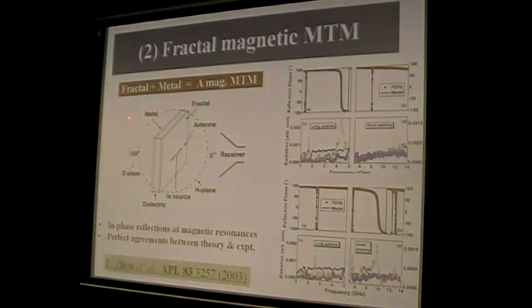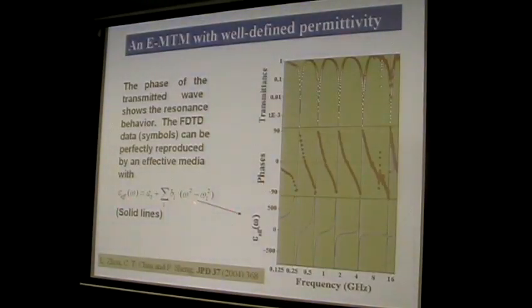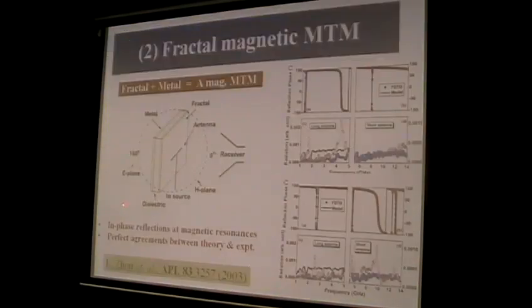Now I'd like to introduce the magnetic material. You can see that for the single plate of metallic fractal, the effective medium shows that this system is basically still an electrical response. So the question is, how can we make it magnetic? We found that we can add another metallic sheet on the back of this substrate. So this inside layer is the dielectric substrate, and this is a metallic fractal plate. And on the other side, we have a perfect metallic sheet. And this whole three-layer sandwich structure is actually a magnetic material.